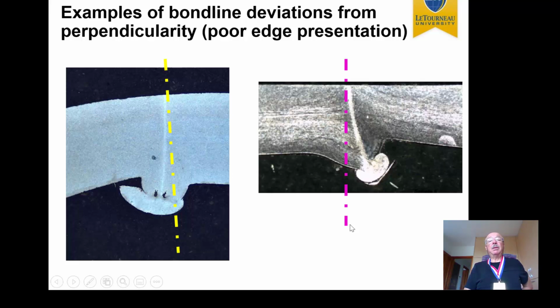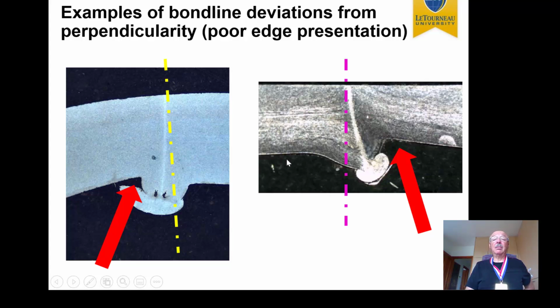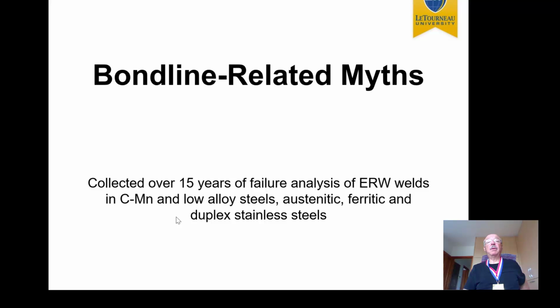At the same time, its orientation is important. For instance, if the bond line is not perpendicular, or radial as it should be, but is skewed like this, or in this case, clearly there was a poor edge presentation, and that causes not only thinning of the wall. Notice that after shaving off the excess material, this part of the weld is much thinner than the other side, so that's not good. The pipe could explode, and it also produces a notch. So again, if the bond line is not perpendicular to the surface, or radial, that's also a problem with overscarfing. I just mentioned that.